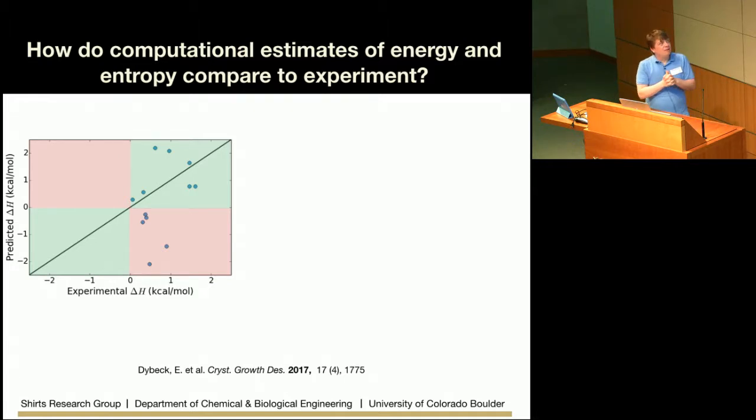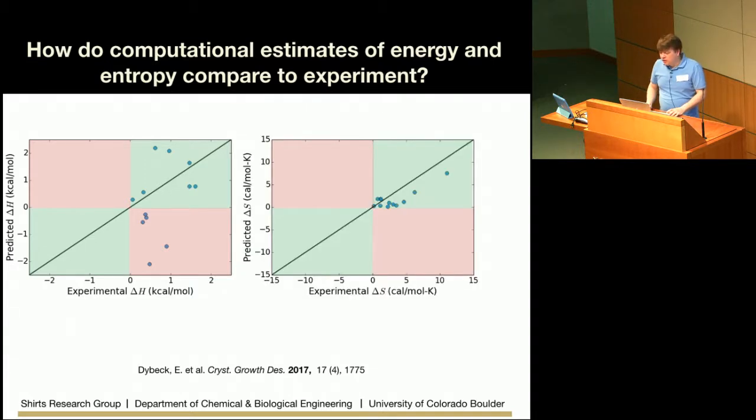So probably at least on the range of, for enthalpies, a third, half of a kcal. So what you see is that OPLS-AA, and any fixed charge potential, it's not just OPLS, is pretty bad at predicting enthalpy of crystals. This is why a lot of people doing crystal structure prediction have really driven towards using quantum mechanics in order to get these right. But if you look at the entropies, they are all much closer.